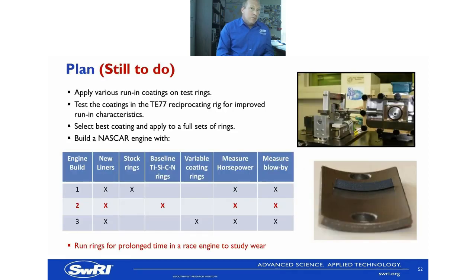What we still need to do to prove this out a little more is to run a prolonged time in a race engine, just to make sure that we've got the durability there that we're wanting to have, and that we don't see any tick up in wear due to anything happening. We also would like to run the baseline rings in the NASCAR engine as well, just to get a baseline there of the TISICN ring that this technology came out of, which would really show how the variable coating is actually changing the run-in and has an advantage effect.